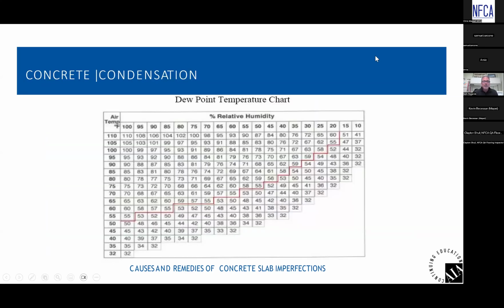Okay, condensation. That's another situation that can happen out on site. This is a typical dew point chart, and it's pretty simple. If you gather specific information about a project, you can see whether you're close to dew point or not. If we take your ambient humidity, your ambient temperature, and the substrate temperature at the surface, you can quickly see how close or how far you are away from dew point by using a chart like you see here and plugging in the values.